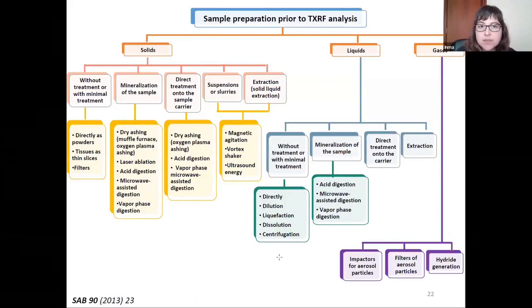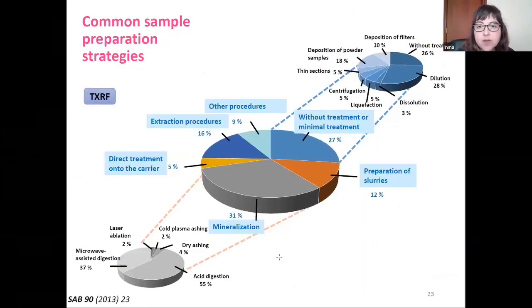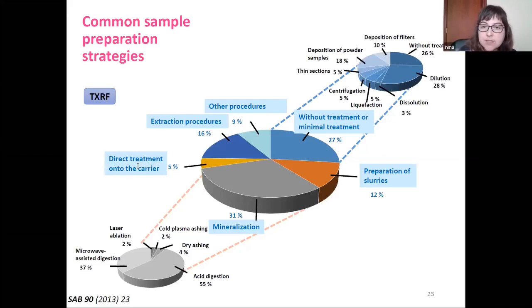As we can see in this scheme, there are a lot of possibilities for sample preparation prior to TXRF, for solid samples, liquid samples, and also for gases. Probably the most common sample preparation strategies are the preparation of a suspension, the mineralization by acid digestion, also the extraction procedures, and it is also important to take into consideration the direct analysis of solid samples, for example, as thin slices of tissues, or also without treatment or with minimal treatment, that can be, for example, dilution of aqueous solution.